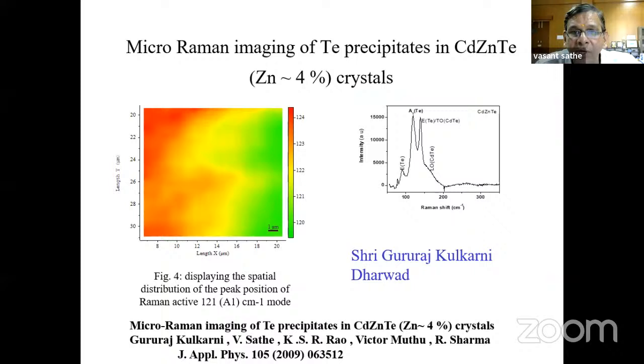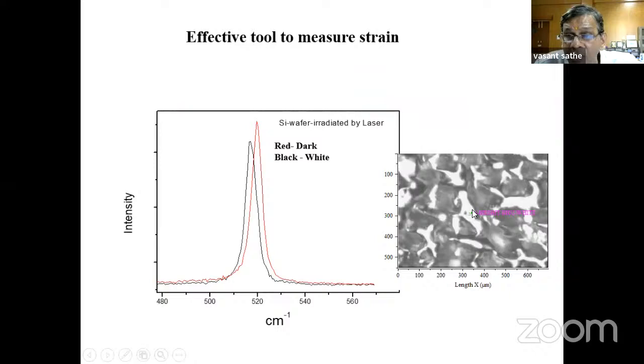So as I said, it is highly sensitive. This is actually a silicon wafer, and some laser irradiation was done onto it. After the laser irradiation, we found that there are white and dark patches. So you see immediately, because the strain or the nature of the silicon bond is slightly distorted in these two particular phases. So you can see that in the white portion, and this is 520, it is shifted, and this shift can be recorded very easily.